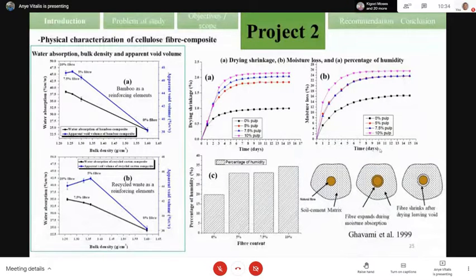By studying the density, apparent volume, we realize that the more we introduce the fiber in the matrix, the more we increase the water absorption and porosity, and there is a reduction of the density. This is due to the fact that the fibers have a low density and also have a high absorption capacity of water. So that is why the more we increase the fiber, the more the water absorption increases.